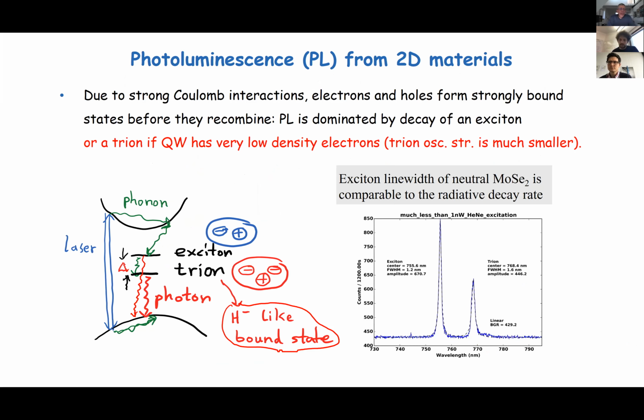So now, if you want to explore the material, you do so-called photoluminescence, which means that you use a laser to excite electron hole pairs, which relax. And as they relax, the electron and hole, because of the Coulomb attraction between them, form a bound state. This bound state can decay, emitting a photon. Because of the strong correlation between the electron and the hole, the decay rate can be extremely fast.